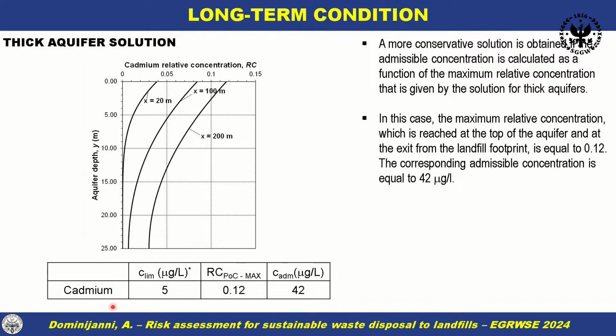And a still more conservative solution is obtained if the admissible concentration is calculated as a function of the maximum relative concentration that is given by the solution for thick aquifers. In this case, the admissible concentration in the waste leachate is found to be equal to 42 micrograms per liter, which is about 50% of the concentration obtained from the solution for thin aquifers.